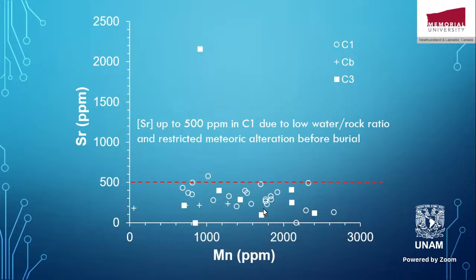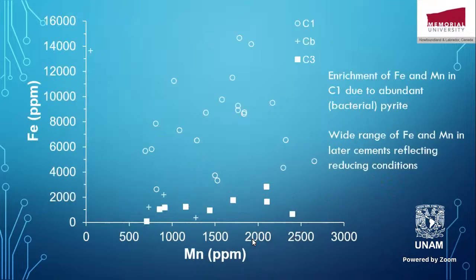Well, if we look at the strontium and manganese cross scatter diagram, we can see here that all of them have values below or close to 500 ppm strontium, a little bit below, but a few samples from the C3 and C1 are above 500. This can tell us that there were some aragonitic shells in the sediments. Also, it could be a low water-rock interaction ratio, not a high water-rock interaction ratio. So the depletion of the strontium was not very severe, but you can still see the enrichment of manganese is high. So the levels were enriched with manganese.